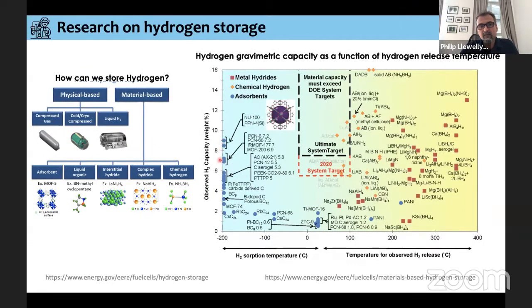And what we see from this diagram, or at least from this work, is that a lot of the studies have taken into account work that's been carried out at 77 Kelvin. And even if we do have a medium to high uptake for some materials, for example NU-100, which has this structure here, we can see that there's a lot of engineering in terms of materials to get towards a DOE target if we want to look for storage of hydrogen. I'm guessing for use in cars, for example.